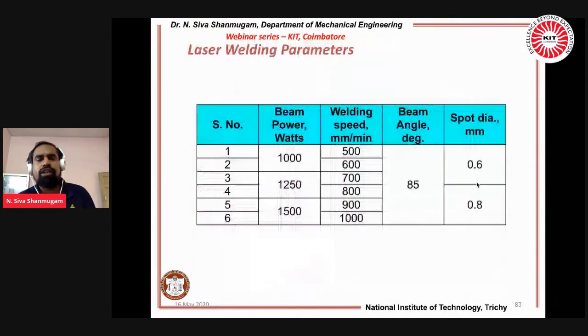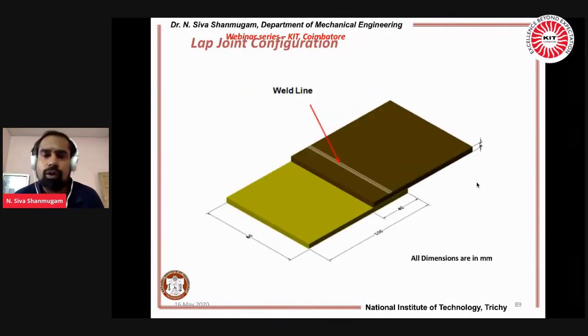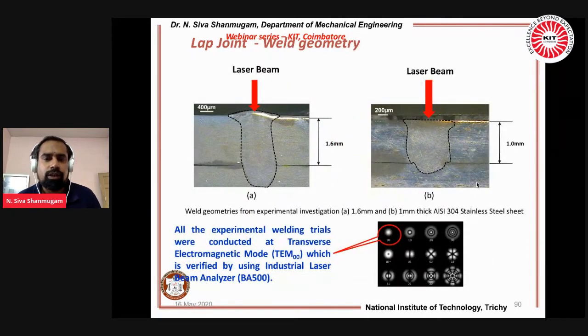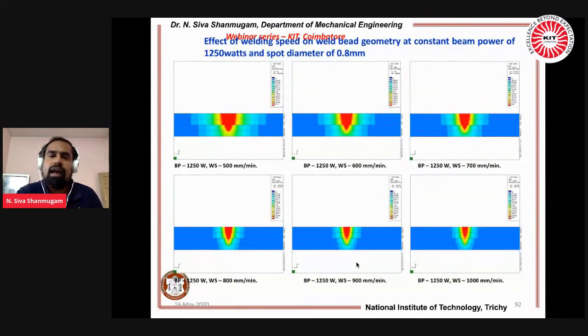Okay, so this is for different joint configurations. I already told you, we have simulated the T-joint, and we have simulated the lap joint. So this is the TEM00 mode, TEM10, TEM20, so many modes are available. This is for the lap joint, and we have made the simulations with the sheets placed one over the other. So what is the appropriate power required to penetrate the bottom sheet? You see, the top sheet is penetrated and it is getting into the bottom. You see, when you are operating with this beam power and welding speed, you are not supposed to penetrate the bottom sheet. So these are all to cross check whether the beam power is adequate to achieve full penetration. This and all you can achieve.